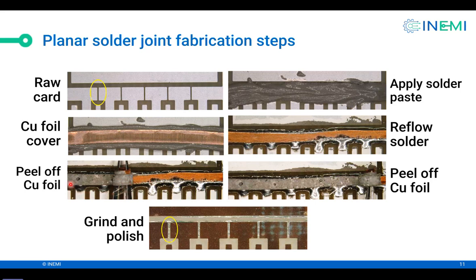We reflow the solder, and then we cool it down, and here we are peeling the foil. So what we do is we hold the foil with a tweezer, and you can see the 2 tongs of the tweezer, and we rotate the tweezer like a sardine can. We peel the copper. And the amazing thing is the solder, even though it's metallurgically bonded to the copper, when we peel it, the solder stays on the circuit board. So this came as a real surprise to me. So you can see here, the solder is on the circuit board. We have removed the copper foil.